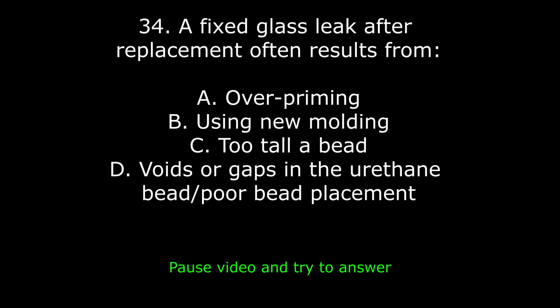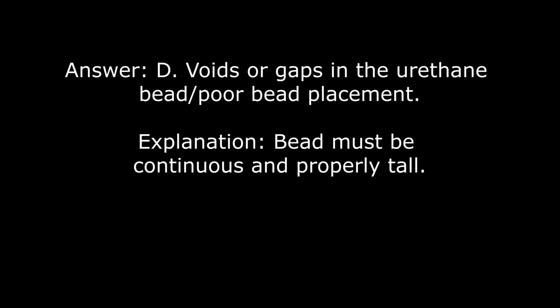34. A fixed glass leak after replacement often results from: A. Over-priming. B. Using new molding. C. Too tall a bead. D. Voids or gaps in the urethane bead or poor bead placement. Answer: D. Voids or gaps in the urethane bead or poor bead placement. Explanation: bead must be continuous and properly tall.